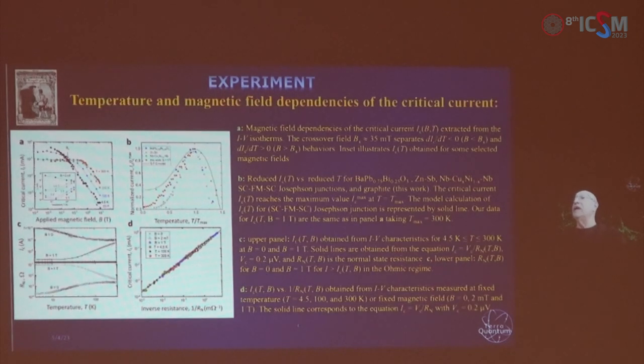Then, okay, these are the measurements, again summarizing our results. So this is the critical current dependence upon the applied magnetic field and temperature, which shows that there is some critical point which separates the region where critical current decreases with the increase in magnetic field or temperature from the region where it increases.